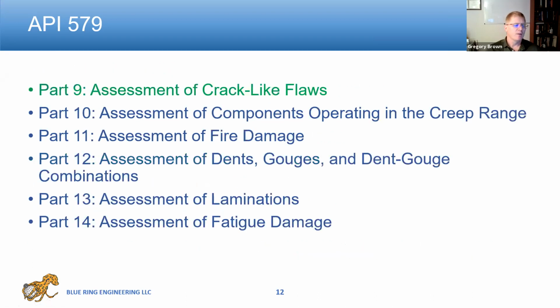Part 9 really to me is one of the most important parts of the standard because it's really the most powerful, assessing crack-like flaws. This could be weld defects, lack of fusion. This could be fatigue cracks. This could be stress-oriented hydrogen cracking. This could be stress corrosion cracking. A lot of different types of cracks can occur. Part 9 allows you to assess those. And with a level 3 assessment, you can actually start doing crack growth calculations to do fatigue life, for example. So we'll go through that in detail.